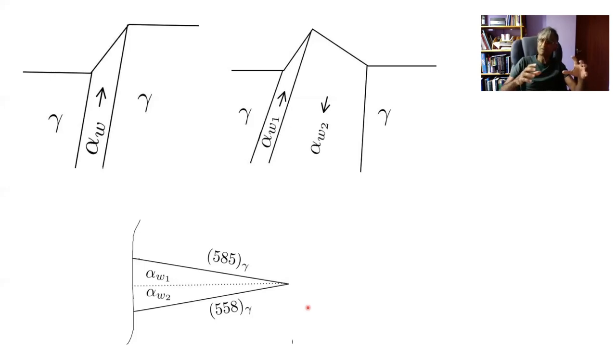One of the detrimental aspects is that you have to nucleate two plates together. Those two plates have to be of a kind which accommodate each other's shape change to some extent, which means that the nucleation rate is reduced, because the probability of finding two appropriate nuclei is going to be smaller. Therefore, the Widmanstätten ferrite structure is very coarse compared with, say, bainite, and its mechanical properties may not be optimum with respect to toughness and the deflection of cleavage cracks.